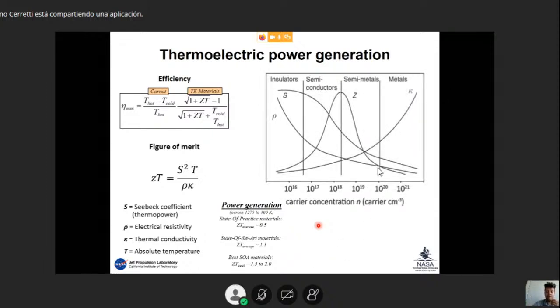But if we consider how all these parameters are strictly interconnected, we realize optimizing ZT is not really such a straightforward task. We can see that as a function of the carrier concentration, if we, for example, reduce the charge carrier concentration, we will have an increase in the Seebeck and a reduction in the thermal conductivity, which is positive, but at the same time we will also increase the electrical resistivity. So we need to find the balance, tuning all these properties to find the maximum.